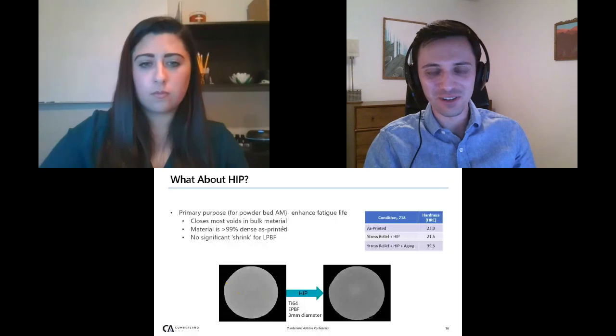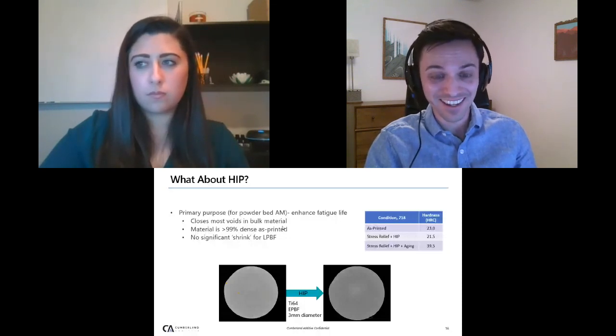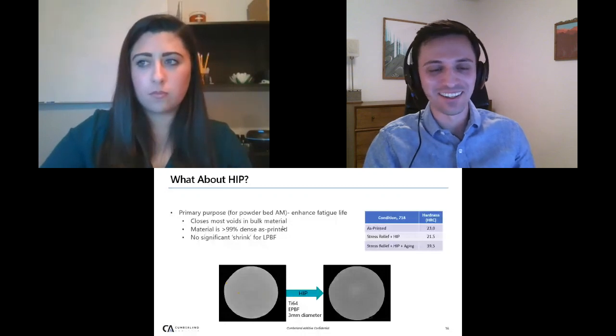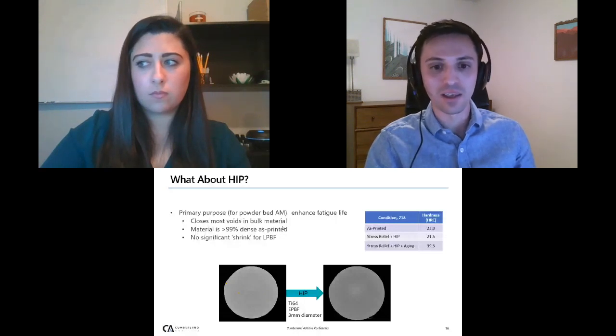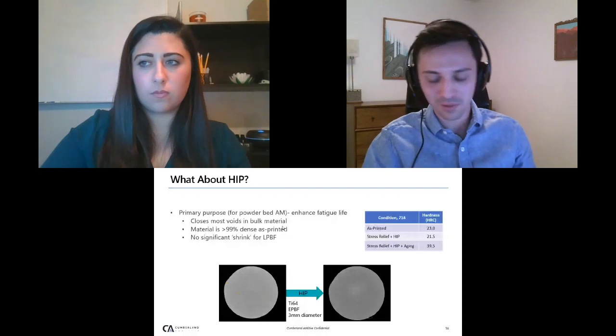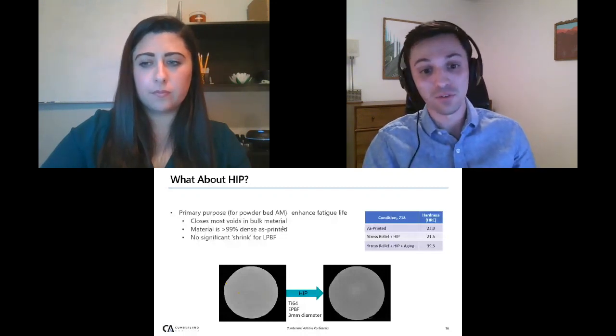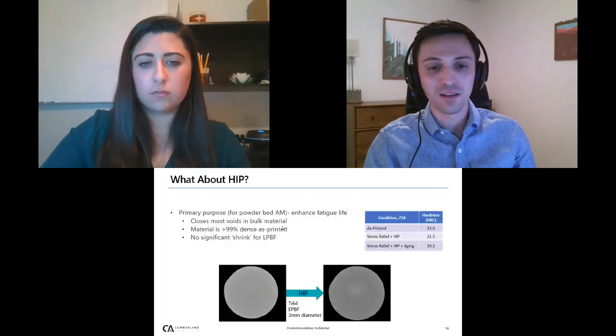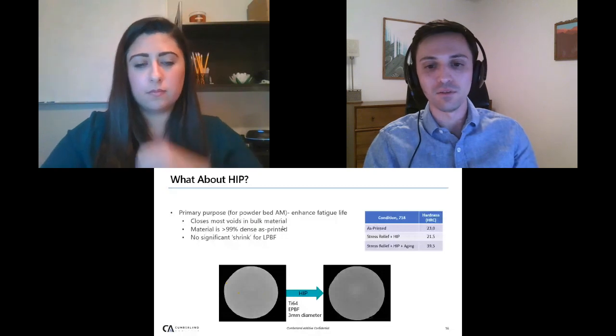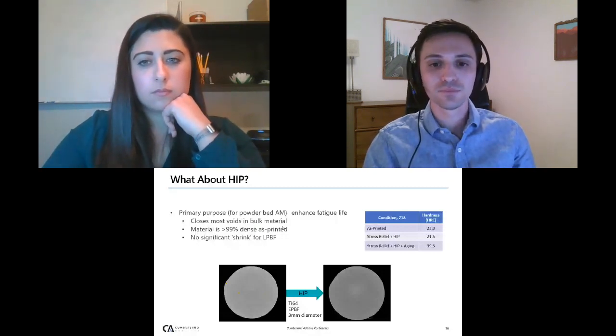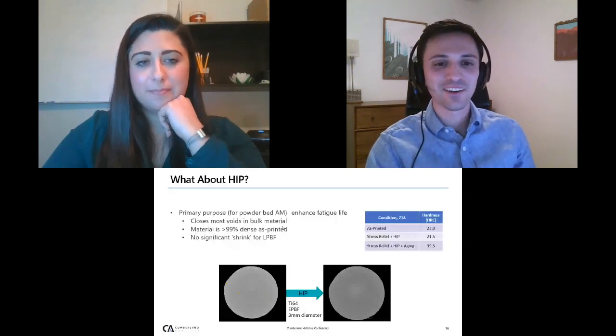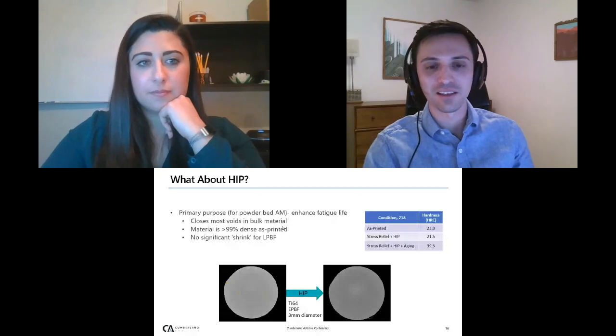Unfortunately, I think my figure there is not high enough resolution to hardly see it. But if you look real carefully, you'll see some little yellow splotches. Those splotches are voids that are identified in a CT scan image that we're depicting before and after HIP. And in this case, we were able to show that those voids that existed pre-HIP disappear after HIP. You can only even find those things by using a really high resolution CT scan. And this is a tiny sample. The diameter is 3 millimeters, an 1/8 of an inch. And the voids are all healed there. Sorry, the presentation's jumping around a little bit. Okay, so now we'll talk more in depth about non-destructive testing like that CT scan.